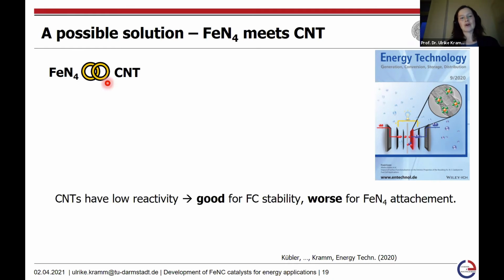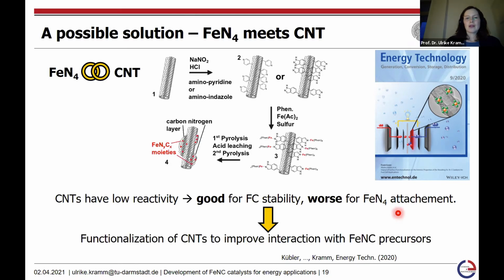The CNTs have, of course, the advantage that they are very good for the fuel cell stability, as they have a low reactivity. But due to this low reactivity, they are also worse for the attachment of the FeN4 centers. So he thought that this surface functionalization, which he also performed in order to get a better interaction between the CNTs and the platinum nanoparticles, might also be a good strategy to directly bind the FeN4 centers to the surface-functionalized CNTs, then perform the pyrolysis to form our final catalyst material.